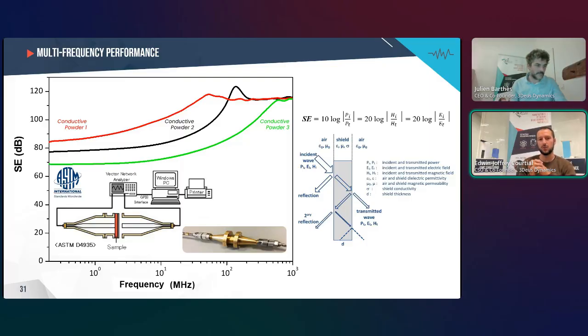The overall shape of the curve indicates that our materials operate mainly through reflection-dominated shielding rather than absorption. This behavior is consistent with the conductive percolation network within the silicone matrix, ensuring efficient reflection of incident electromagnetic waves across the test spectrum. Now that we have validated the shielding performance under static conditions, the next question is, how stable is this conductive network when the material is deformed in tension or compression, as it will be in real joints?